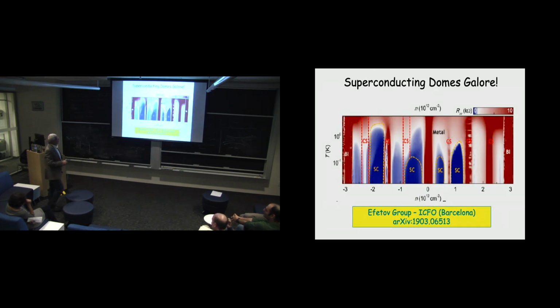The biggest difference is that the early samples, and I think we can say the samples with more twist angle inhomogeneity, did not show insulating states at neutrality. In more homogeneous samples, the strongest insulator is at neutrality. So one thing I've wondered about is why this gap at neutrality is apparently more sensitive to twist angle disorder than the other ones.